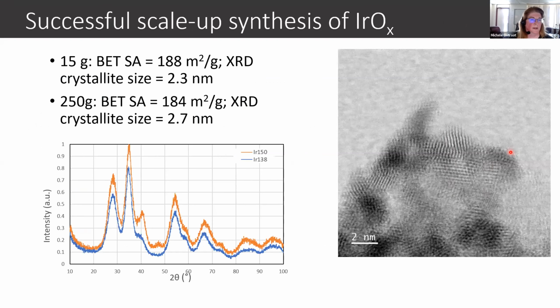Moving now a little bit to the iridium oxide work. Again, very important in the electrolyzer anode area. And here we've spent a lot of work trying to develop and also scale up iridium oxide synthesis from about 15 grams to 250 grams. As many of you may know, iridium is a pretty difficult material to work with. It's very acid stable and has other characteristics that make it ideal in electrolyzers, but it can also lead to somewhat challenging chemistries.